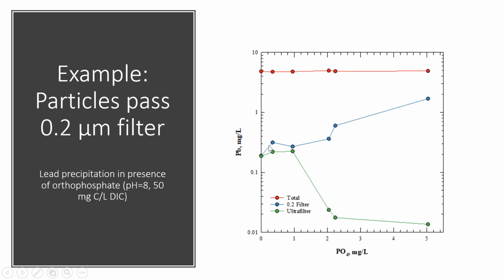And a reason for that, and this is important for anybody doing solubility experiments, is that the demand for orthophosphate is too great. In other words, there's too much lead and not enough orthophosphate to meet the demand of all the lead in the water. So what you end up having is a mixture of lead carbonate and lead phosphate. Very important point. In other words, there's no soluble phosphate coming through these filters, and that's because it's all being bound up.